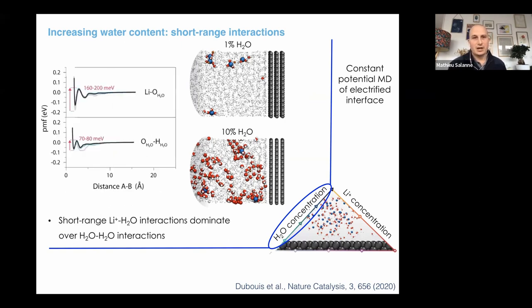Then if you look at the interaction between lithium ion and water, or between two water molecules, in that case, we just did a simple calculation of the potential of mean force. And you see that the lithium is in fact attracting the water molecule very strongly. And so there is a very strong effect of the lithium on the reactivity. So it means that in this specific system, the most reactive molecules will be the ones that are already coordinated to lithium, sorry, water coordinated to lithium. And putting more and more water will not change things.